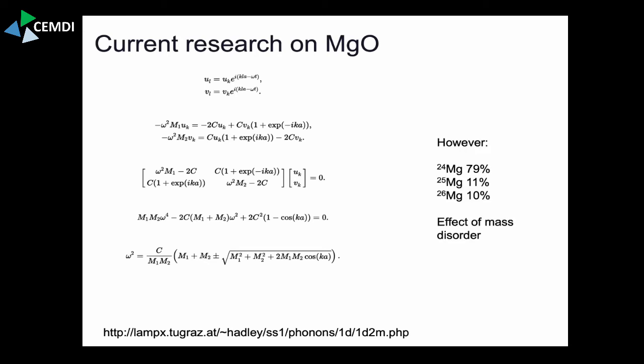Interestingly, magnesium is not a pure isotope. Magnesium has natural isotopes, which are 79% the lightest one, and then 11 and 10% the heavier ones. Now, what happens to that chain if you distribute different masses? It, first of all, will depend on how you distribute them and how you actually make a proper random distribution. But this has been discussed in terms of mass disorder by Cardona in some recent work. Well, he passed away, I think, about 15 years ago, and it was for silicon. And this, I think, was done to show that the silicon peak itself has contributions from this mass disorder, because silicon is not a pure isotope either.